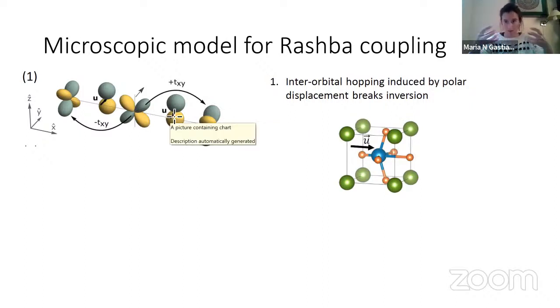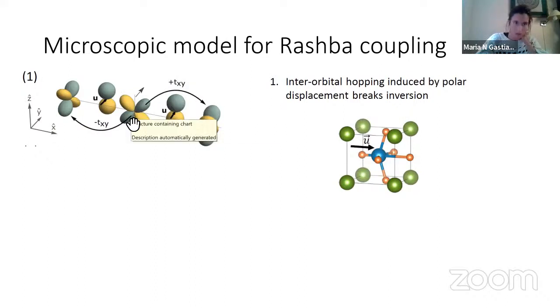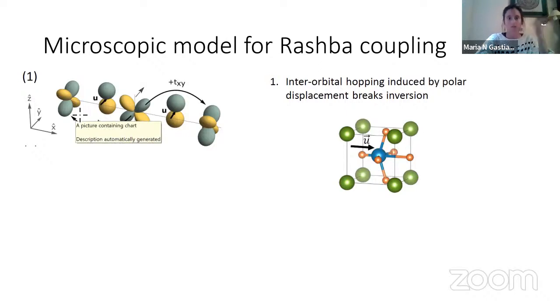Because this optical mode breaks inversion, the hopping that happens to the right and to the left will also break that inversion. So hopping to the right would be with plus t, and hopping to the left would be with minus t. You can even follow that with the colors: blue, blue, blue is positive, and now blue, yellow, blue is negative. So that's the first step.